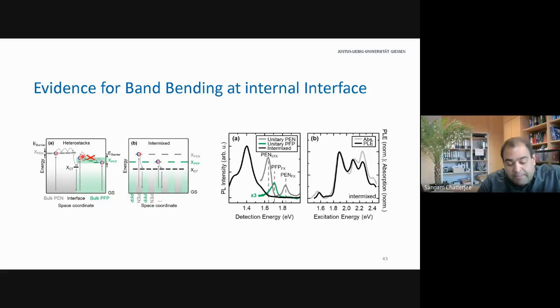And that's why, apparently, the PFP doesn't seem to contribute to any of the CT state populations, because the molecules you excite in the PFP, the excitations diffuse away from the interface into the bulk of the material. And that's why it seems that this is only populated from the pentacene side. But keep in mind, to have the state present, you actually need the interface. So the orbitals do contribute. This is the difference between having states and having a population.